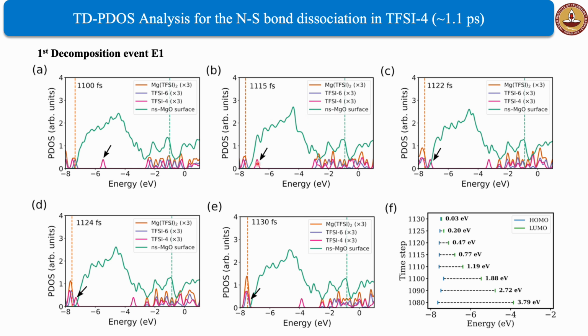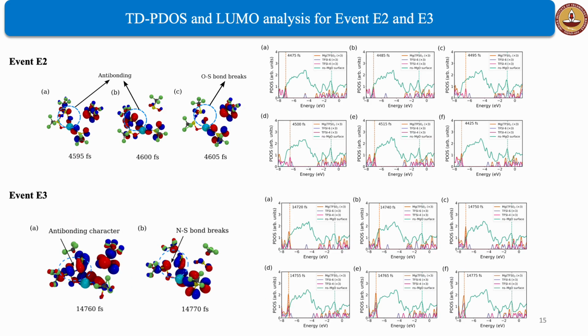As time progresses, the LUMO of the TFSI-4 shifts downwards and approaches the valence band edge of the surface. At 1124 femtoseconds, we can see there is an overlap between the valence band edge of the surface and the LUMO of the TFSI-4, marking the onset of the charge transfer. By 1130 femtoseconds, the LUMO of the TFSI-4 has become a part of the HOMO manifold, indicating that the charge transfer has occurred. Similarly, we can understand the remaining two events, E2 and E3.